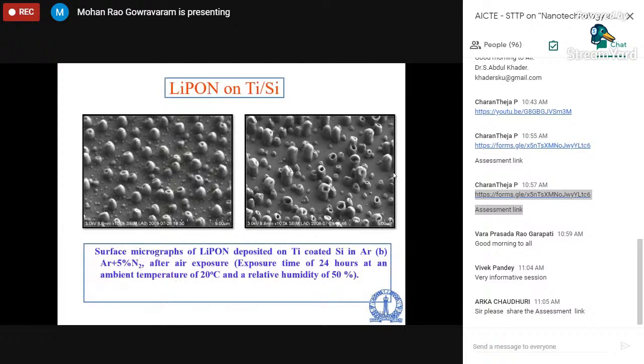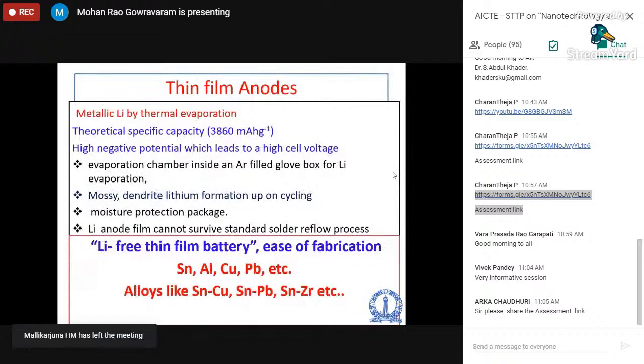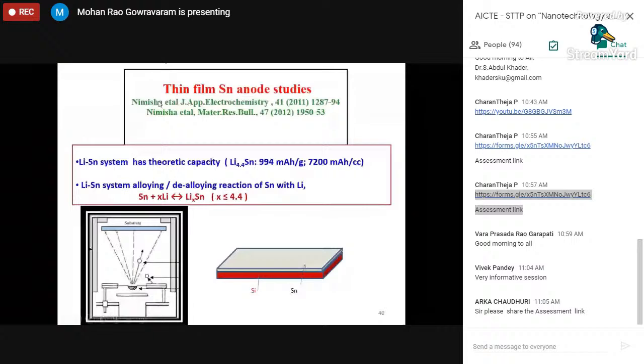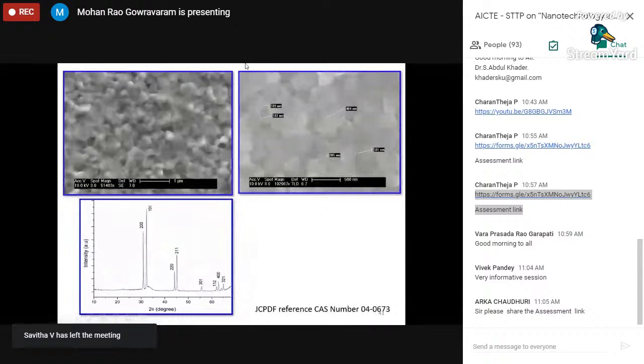Now you go to your third layer, that is the anode layer. So now what we want here is that it is the anode which is taking this volume expansion and contraction business. So it should be a soft material and it should be a porous material. Soft materials are tin, aluminum, copper, lead, etc. But lead is heavy. So we arrived at the tin layer, that is Sn. So you deposit Sn because it has a low evaporation temperature. You deposit by the evaporation process, and this is how you get the film.